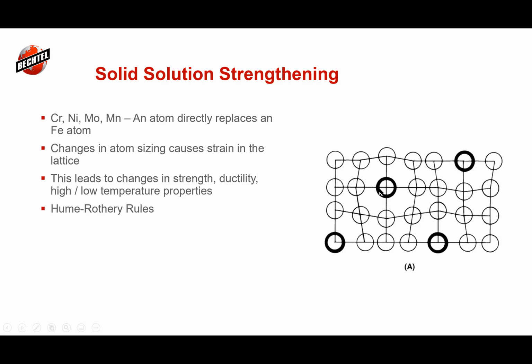atom inside of the iron, it kind of stretches it and pushes around its nearest neighbors. And that change of putting a bigger atom into the iron matrix has a tendency of stiffening it, of locking up that matrix. And that allows us to increase the strength and change the ductility, changes the yield strength and the tensile strength. And the basis for that is called Hume-Rothery rules.